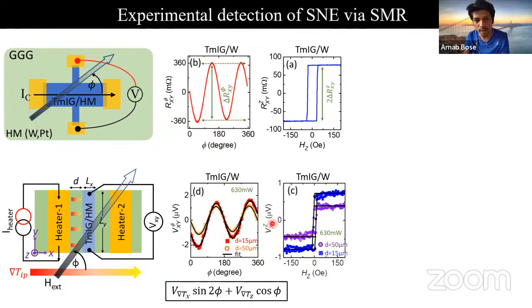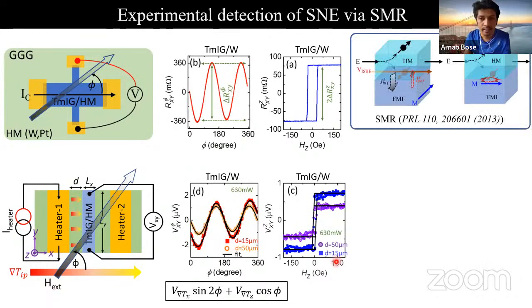So these signals are quite similar. Only a small difference is that for this case, we have an additional cos phi angular dependence that originates from the longitudinal spin Seebeck effect. From this, we can also know how much is the unintentional out-of-plane thermal gradient we have when we try to create an in-plane thermal gradient. Now we need to understand the origins.